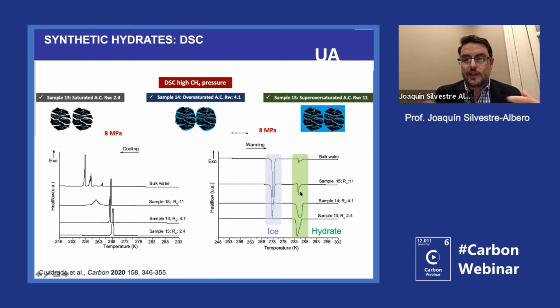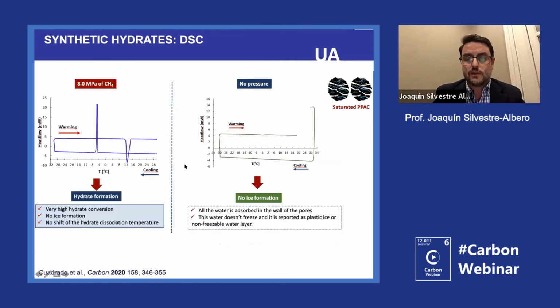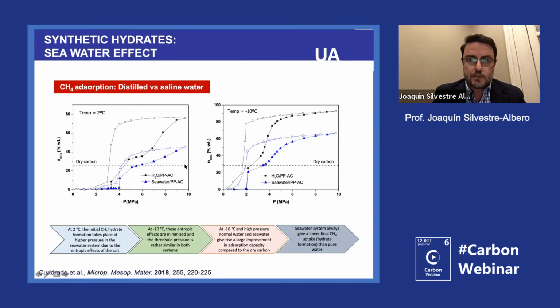So we need to fill the carbons with a lot of water. This is, for instance, the experiment with 11 grams per gram. And there, of course, we have so much water that we see the ice melting and the methane hydrate melting. But this is very important because this is showing that with carbon, we can convert all the water to hydrates in only, as I say, 1 hour of experiment. These experiments I will skip.